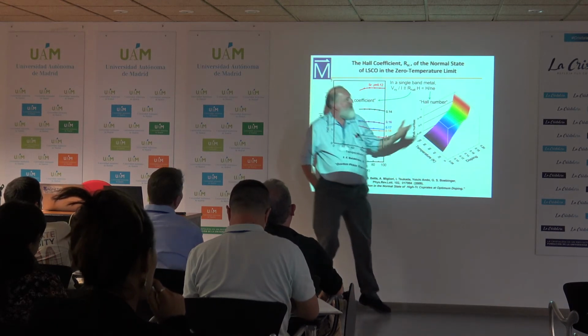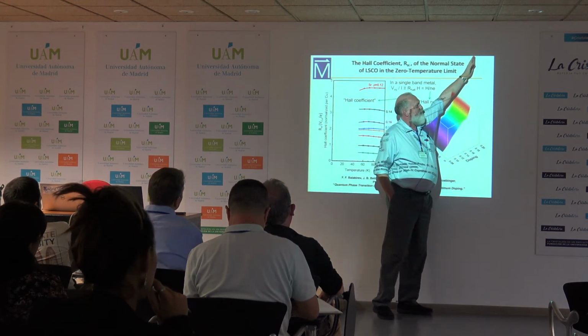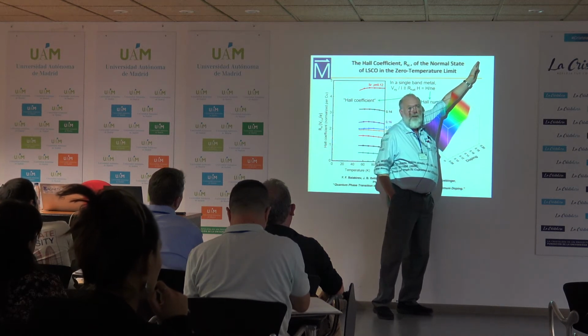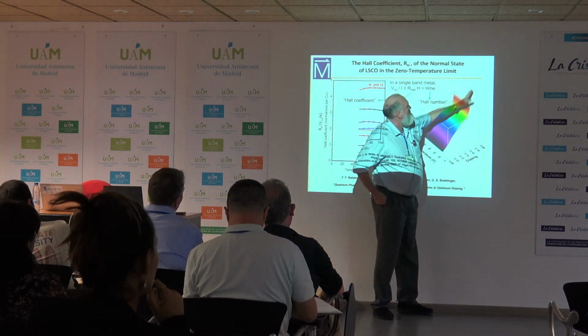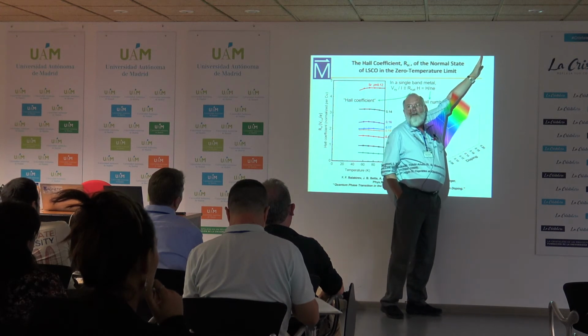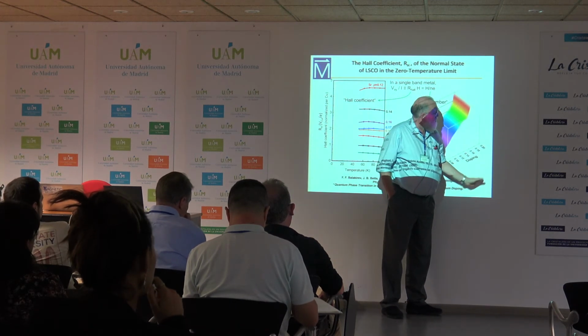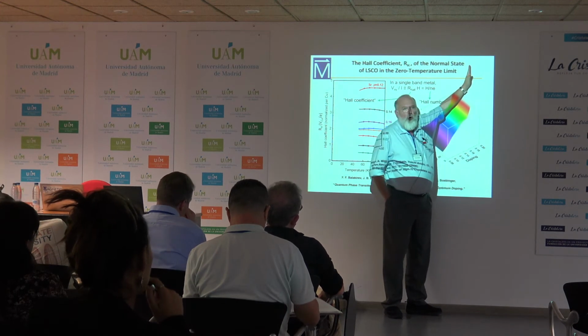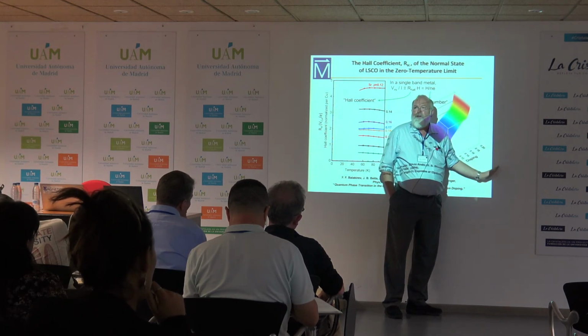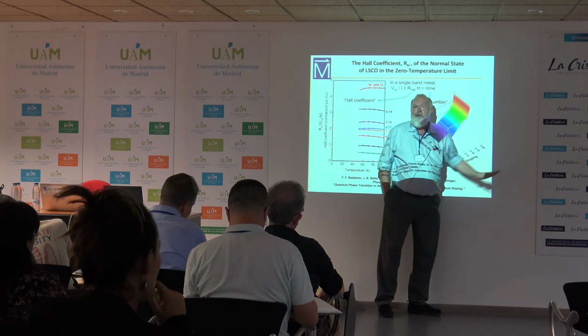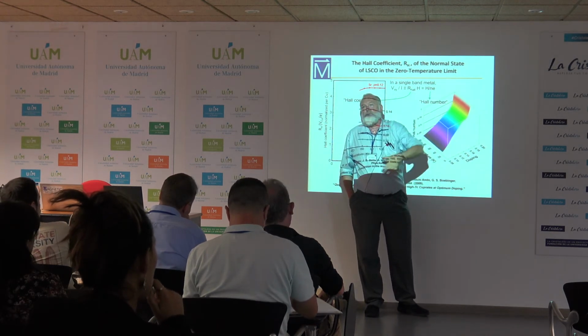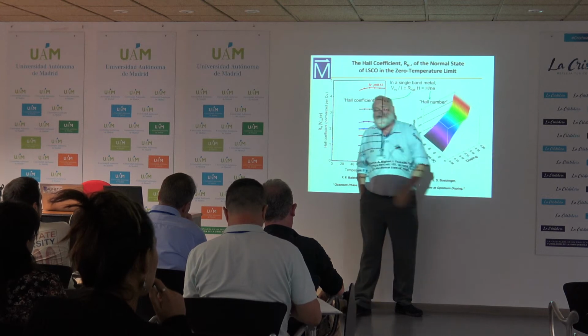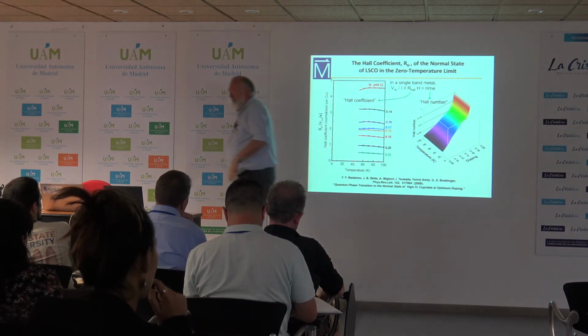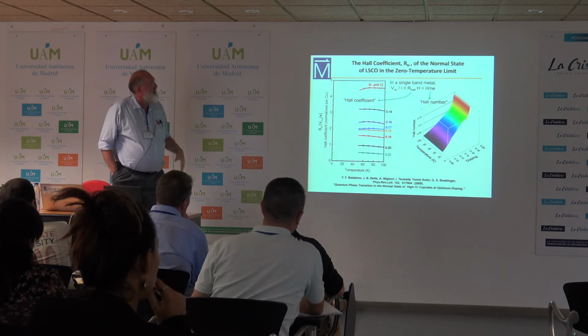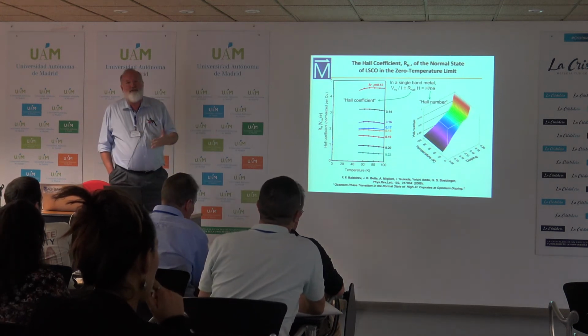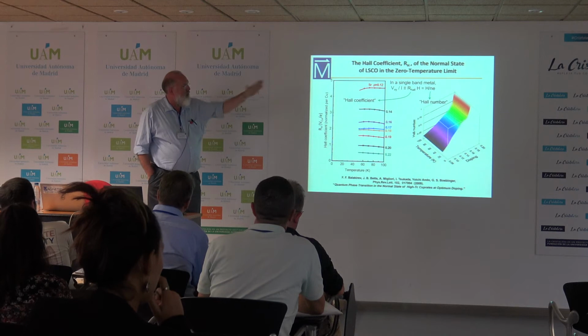And in fact, at least in LSCO, what I think is happening, because we measure this all the way up to 2 apparent electrons per copper, I think this is just screaming up to be a positive divergence to infinity, because you're going to cross over from hole doped to electron doped, or hole behavior to electron behavior, as you go through the band filling and the curvature of your band changes. And we know, at least in LSCO, that this occurs at around 0.28 or so. And so that's another complication to this whole discussion of whether the systems go from P to 1 plus P.